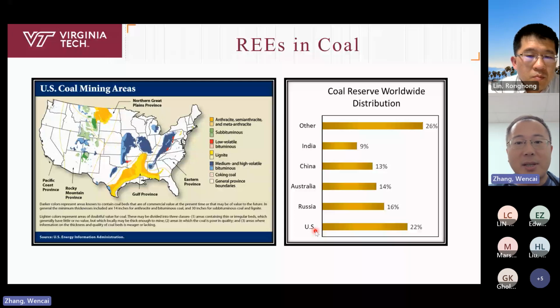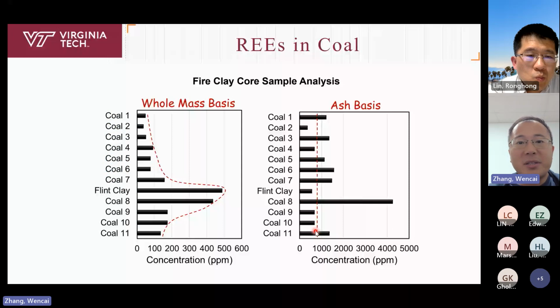In particular, some coal deposits have a very high rare earth content compared with the average content. As you can see in these slides, this is a sample we collected from the fire clay coal seam, which is located in eastern Kentucky. This is the rare earth content in different segments of the coal seam. There are some segments with a rare earth content of hundreds of ppm. For example, there is a flint clay segment of the fire clay coal sample. The rare earth content on a whole sample basis can go up to 500 ppm. This is much higher than the 70 ppm that I was talking about.